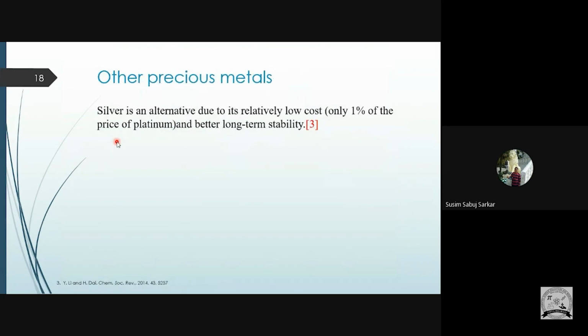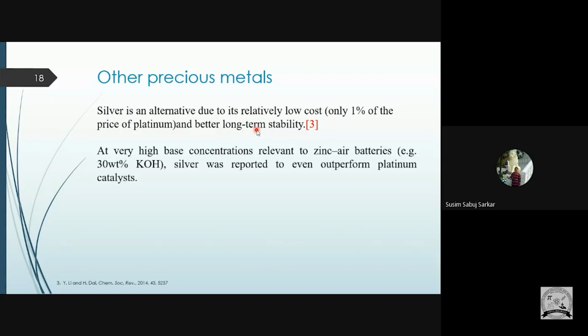Okay, so people try to use alternatives due to their relatively low cost, because silver is only 1% of the price of platinum, and it shows better long-term stability than platinum. At very high base concentration relevant to zinc-air batteries, like 30% weight percentage KOH, which we use, the silver catalyst even outperformed the platinum catalyst.